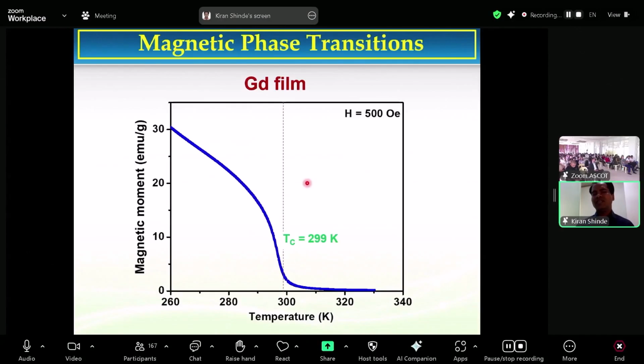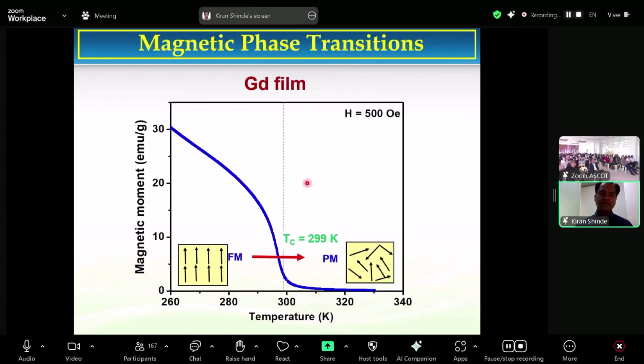So in this slide, I'm going to talk about the magnetic moment with respect to temperature. We have to use this kind of measurement for the determination of the Curie temperature. When we take the differentiation of this magnetic moment with respect to temperature, we can get the Curie temperature. In this slide, I am showing the Curie temperature for the gadolinium material, which is 299 Kelvin. So gadolinium is one of the best materials to use in room temperature cooling application, and it is showing a higher magnetocaloric property around the 299 Kelvin.